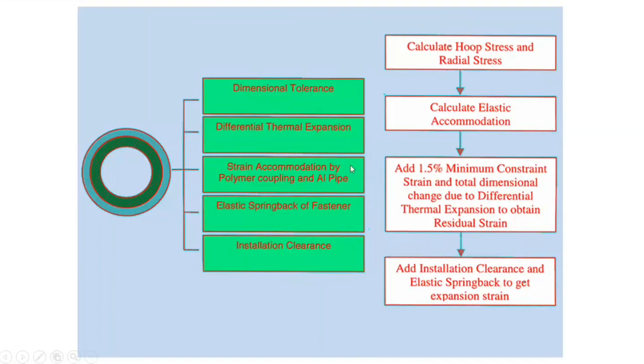So it's some material with only about 3.5 GPa. It will transmit that stress, and it will hold this polymer against the pipe. So that's what it does. In that, it loses some strain, about 0.8% strain in this kind of situation. You start with 6% and you say, I want to have some even at the end of the day. So that's some assurance that there will be some strain which is always locking, and therefore there is a constant stress always acting on it. And we say this 1.5% strain in the design.